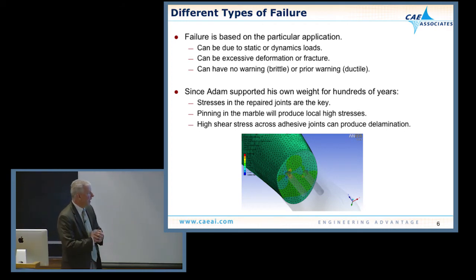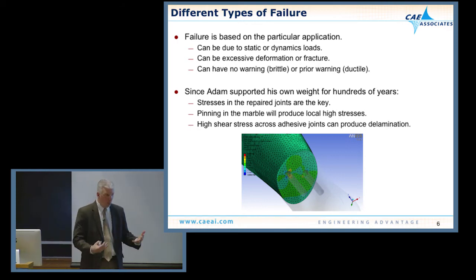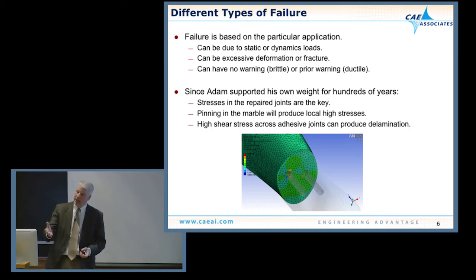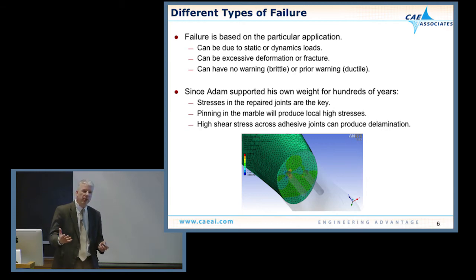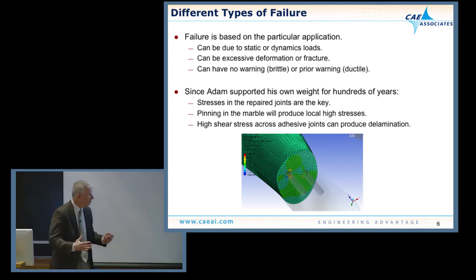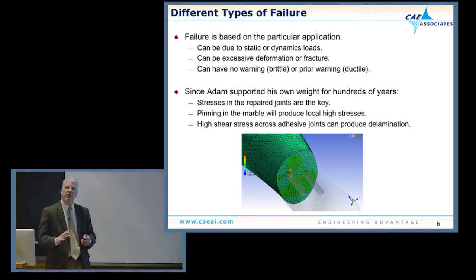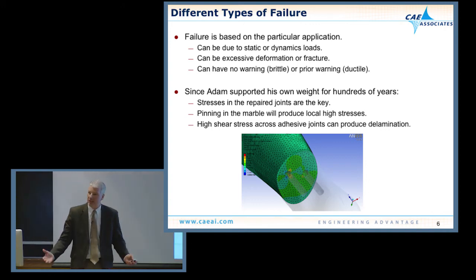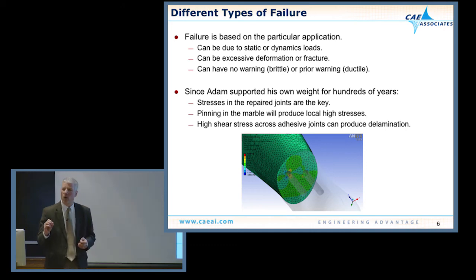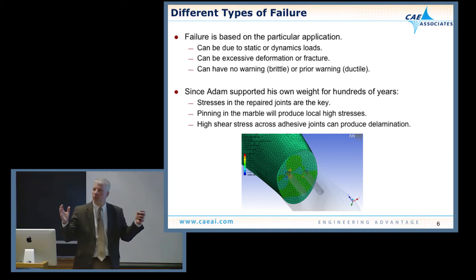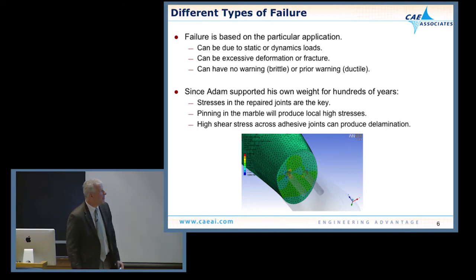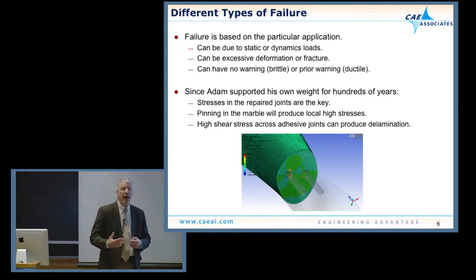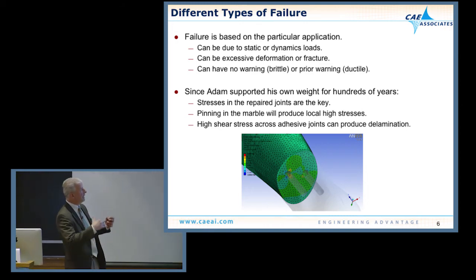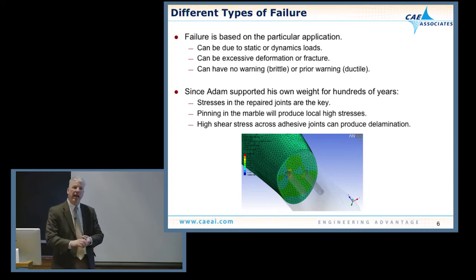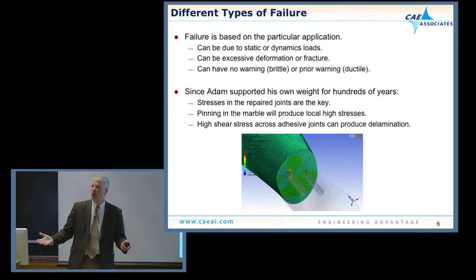In this case, it was pretty interesting because we're dealing with marble, number one, and that's a very brittle structure, and that's why Carolyn had people doing fracture mechanics specimens and testing. Because brittle materials, as we know, if any of you have ever dropped a plate or something else, you know that it's hard to know what the exact stress is that was going to cause that failure, because brittle materials are based on small flaws that under a high load will fail immediately without any warning. So we use fracture a lot of times to describe what happens with a brittle material. So what we're really interested in is looking at brittle fracture in the marble and also looking at delamination where we're going to glue this structure together.